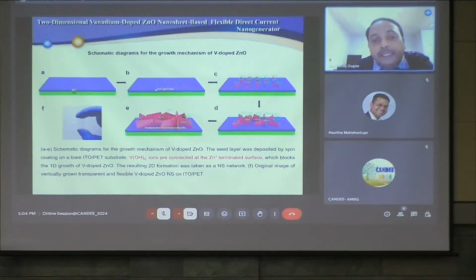We developed the seed layer initially on the substrate, and then we used vanadium as a doping element. Without vanadium, it was nanowires. But when we introduced the vanadium, it changed the surface energy of the nanoseed, and it restricts the growth in the C direction and allows growth only in the A direction, because of some shielding effect created by these vanadium hydroxide ions.